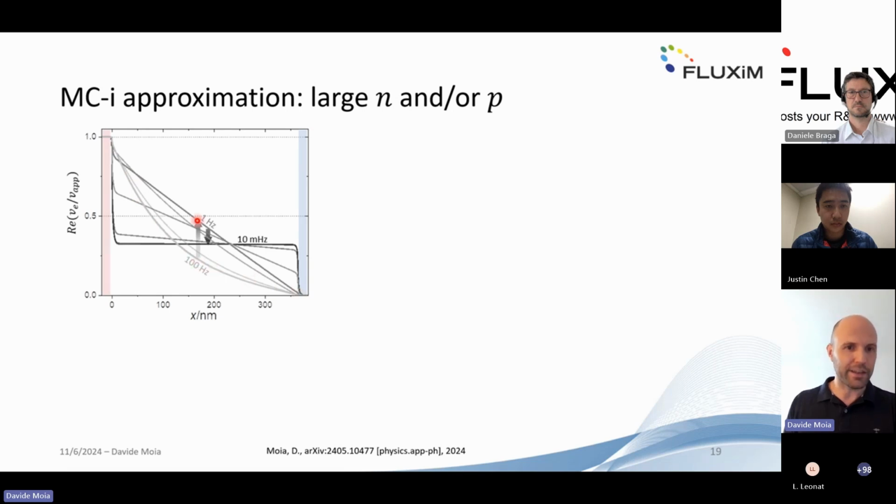We recover the linear profile in electrostatic potential only when ions can redistribute within the bulk. So we have an ambipolar diffusion process happening in the bulk, which is then followed by the space charge polarization effect that I discussed early in this presentation. So essentially the point where we have this change in electrostatic potential that becomes flat in the bulk.